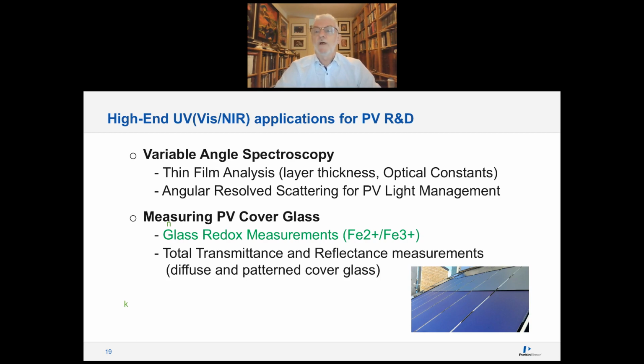Also an important application for the glass industry is the measurement of solar panel cover glass. I will discuss that as well. I will not go into the glass redox measurements, which is also an important measurement. It has to do with iron turning glass green, and if you control the redox state of the glass in the furnace, oxygen activity, you can shift from the iron 2+ to the iron 3+, making it less green, having absorption only at 400 nanometers, getting more transparency for the cover glass.